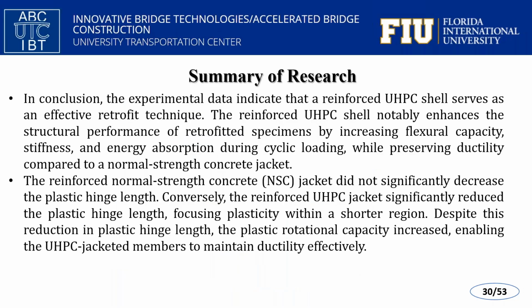In conclusion, the experimental data indicate that a reinforced UHPC shell served as an effective retrofit technique. The reinforced UHPC shell notably enhance the structural performance of retrofit specimen by increasing flexural capacity, stiffness, and energy absorption during cyclic loading, while preserving ductility compared to normal strength concrete jacket.